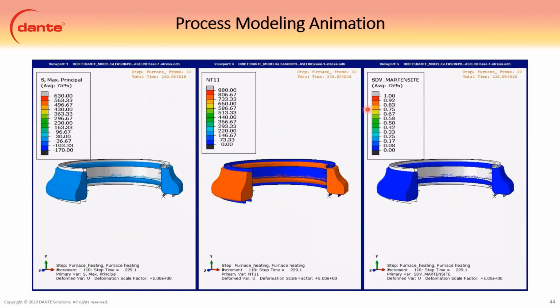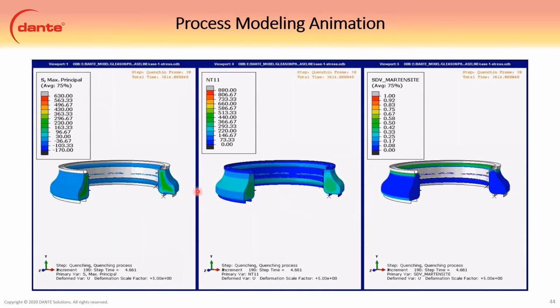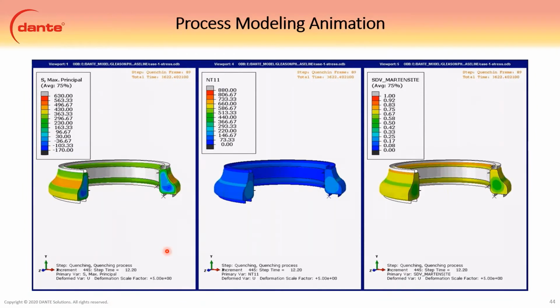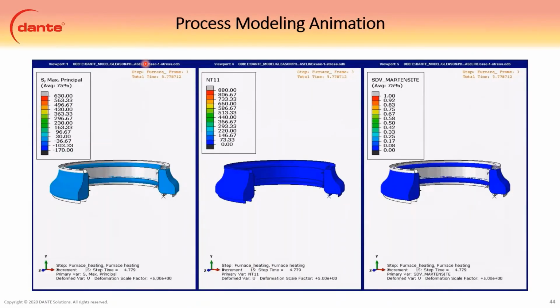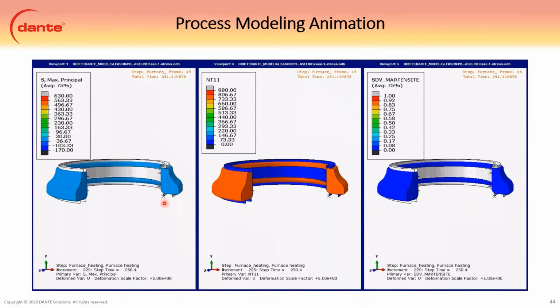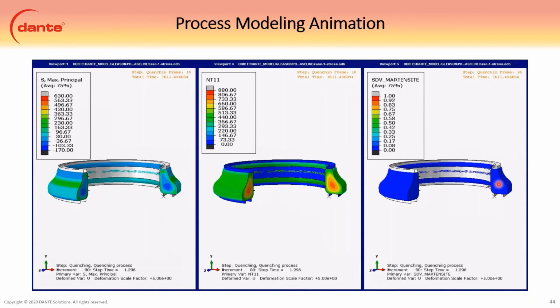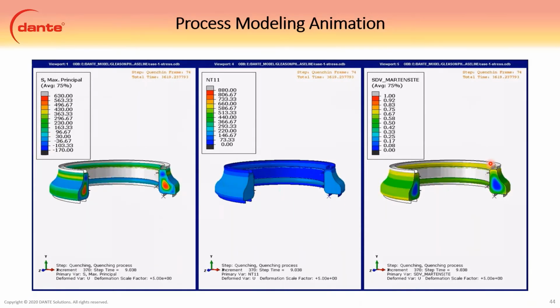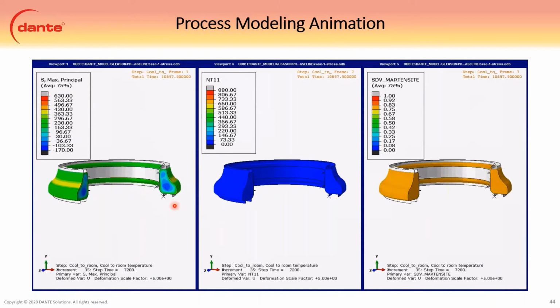So here is an animation. From left to right, we got max principal stress, temperature, and martensite. And our area of concern here is on the bearing race. And you can see it happen right at the end. It goes to red. But the reason for it is the martensite transformation in the core tied to the fact that these dies, this is actually a friction condition. And you still get a high stress over there. But it's because the martensite transformation in the core goes. Once that happens, it pushes everything out and actually tries to open up the bearing race, which puts a bending moment on the bearing race.